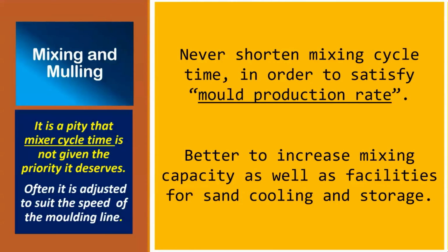So never shorten mixing cycle time in order to satisfy mold production rate. Better to increase mixing capacity. That means go for a bigger mixer which can deliver more tonnage per cycle, as well as facilitate sand cooling and storage. The moment you increase the sand output from the mixer, then down the line, all the areas where the sand is getting converted to a cool sand, mixed sand, and bentonite pre-activation inside the silos, all these things will require additional capacity to match the capacity of the mixer itself.